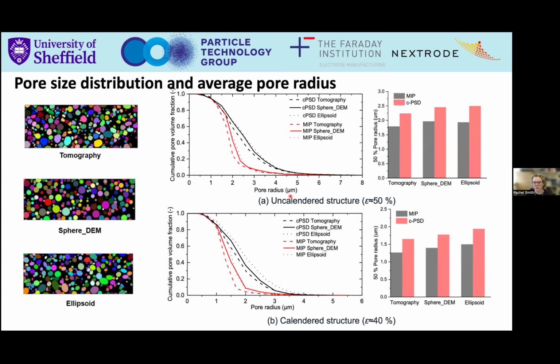And what we basically found was that when we replaced our particles with our ellipsoids, if we go and look, for example, at our pore volume, so basically this is our pore distribution here, what we find is that actually the spheres do a better job for us in this case than the ellipsoid approximations. So now there's not too much difference in it. It's quite close. But that said, we found that basically the spheres work better for us, and we're very happy to hold on to that. And that was validating for our methods, basically.